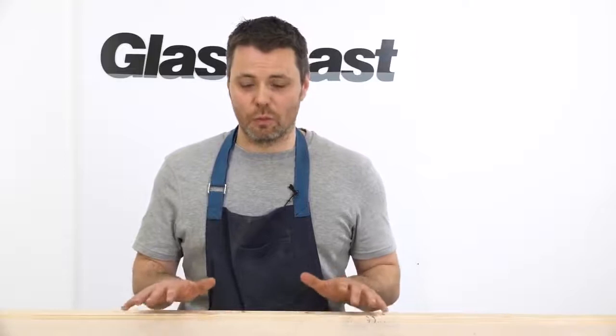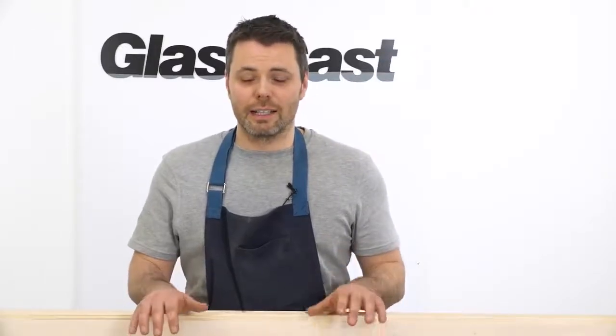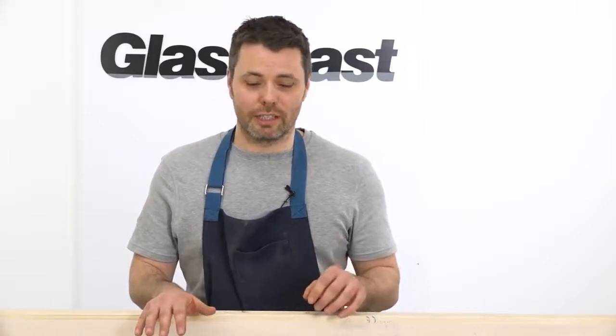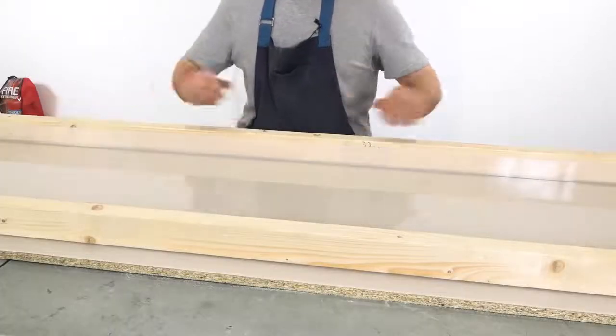So the real key to success whenever you're working with resin and wood in a project like this is to do the process in two separate stages. The first stage is to pour a very thin layer so that we can seal the underneath of the wood and any exposed areas. The second pour is your main pour to bring it up to the top level. Our recommendation for this base layer is to allow 2 millimetres over the total area inside your barriers. We've worked out that we need 1.6 kilograms, and this comes out of the total 10 kilogram requirement.